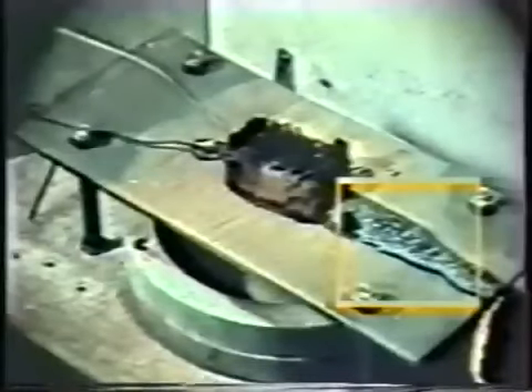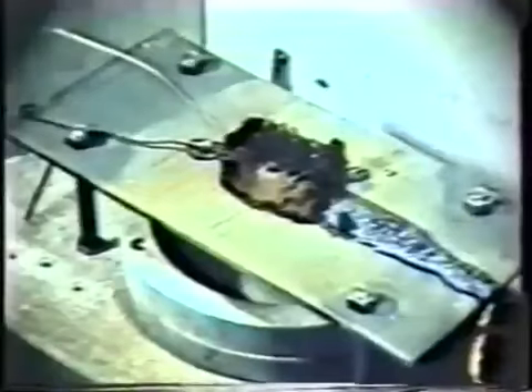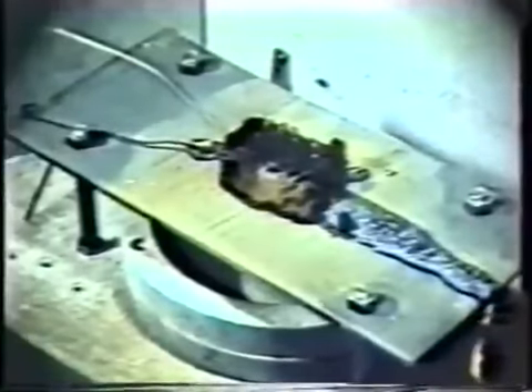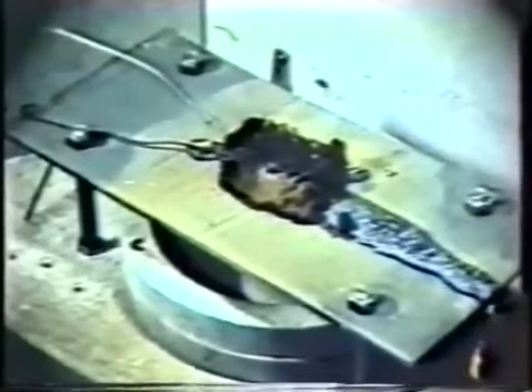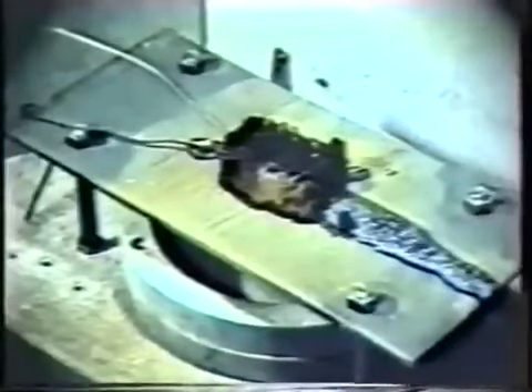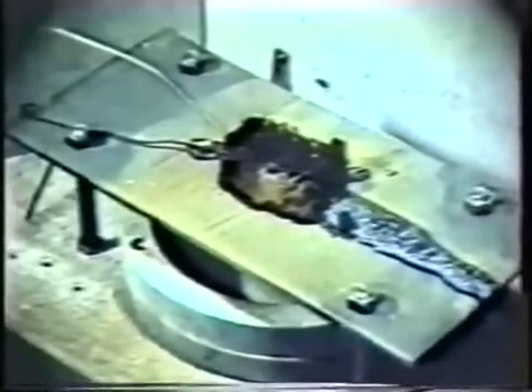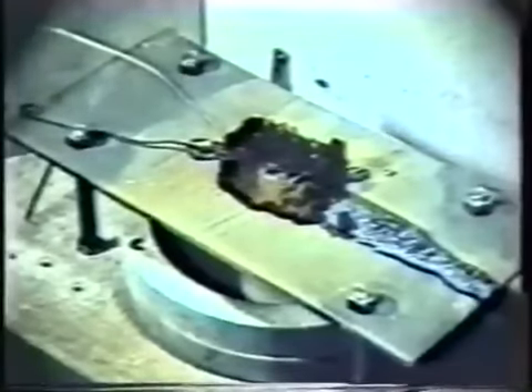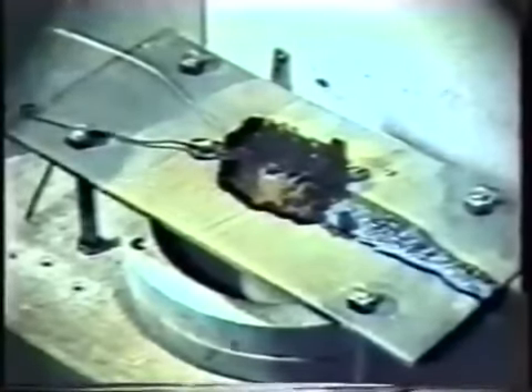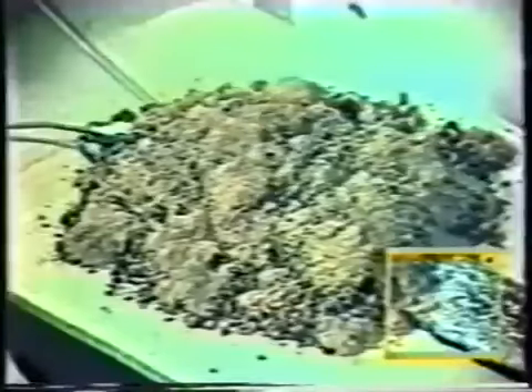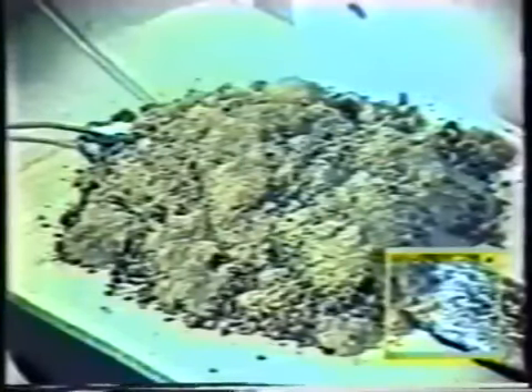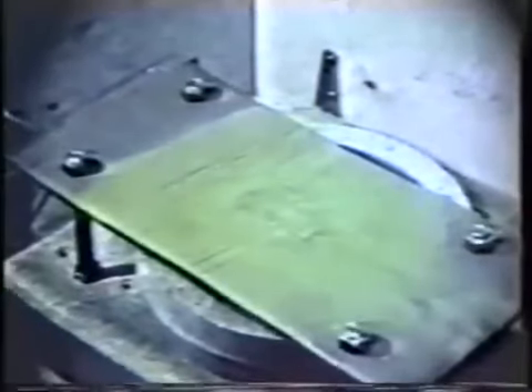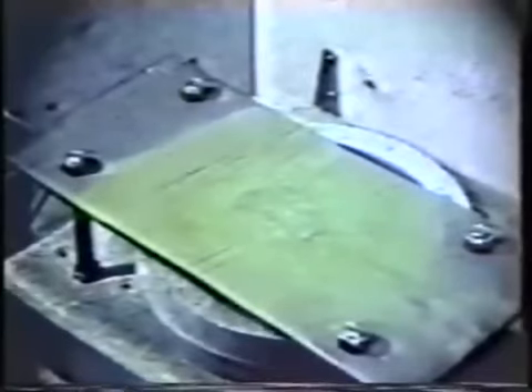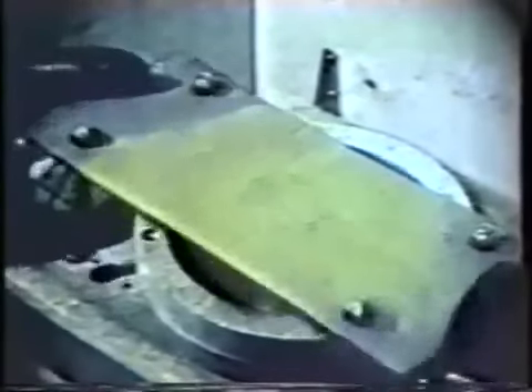The interesting thing here was that the spew of metal coming off from the side indicated that the plutonium inside, again, of course, was molten, but it spewed out onto the stainless steel floor, and the body of the plutonium continued to burn, whereas the spew was cooled enough by the stainless steel floor to go below its ignition temperature, and consequently it was extinguished, which gives you a clue as to what is the best way of extinguishing a plutonium metal fire, and that is use the glove box floor to remove the heat.